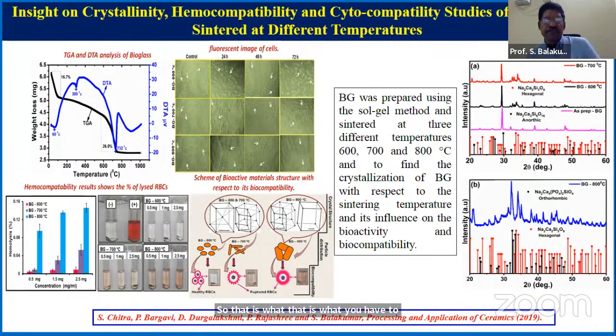So we have synthesized the material by a wet chemical method, at a simple lab level. In the first study, we found that when you vary the process temperature, depending upon the reaction conditions, you get beautiful morphologies, maybe spherical, hexagonal or rods. And we found that they also have very good cell compatibility and hemolysis.